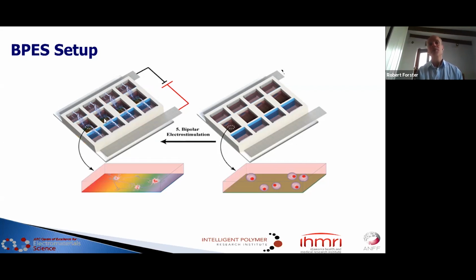Into these chambers she can insert her FTO coated with this biocompatible polymer, and onto that surface the cells are seeded typically at 20,000 per centimeter squared. Now you can turn on the voltage and begin to electrically stimulate these cells, see do the cells remain alive, do they remain viable, and then see can you get them to differentiate from the normal undifferentiated